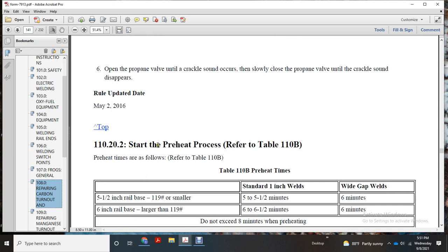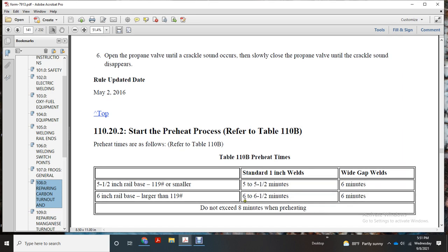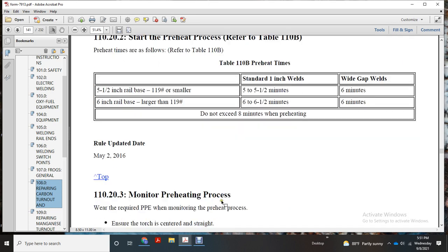Alright, 110.20.2, start of the preheat process. Refer to Table 110B. For a 5.5 inch rail base, number 119 or smaller, preheat 5 to 5.5 minutes for the standard 1-inch gap, and 6 minutes for the wide gap. For a 6 inch rail base, larger than number 119, preheat 6 to 6.5 minutes, and 6 minutes for wide gap welds. Do not exceed 8 minutes when preheating.